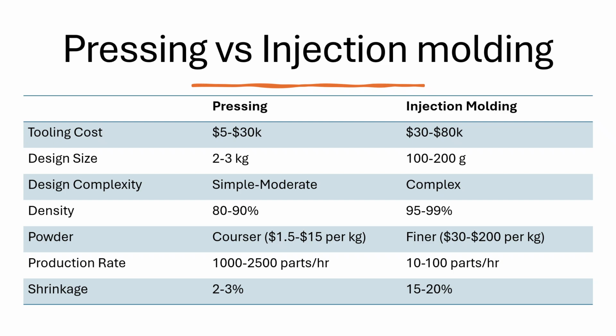The powder used in the conventional press is significantly cheaper at $1.5 to $15 per kilogram because it uses coarse powder versus the injection mold's finer powder, which can cost from $30 to $200 per kilogram. Conventional pressing also has a significantly higher production rate, where it can produce 1,000 to 2,500 parts per hour, whereas injection molding can only produce 10 to 100 parts per hour. This is because injection molding has the debinding step in the process, which takes a significant amount of time and bottlenecks the production.